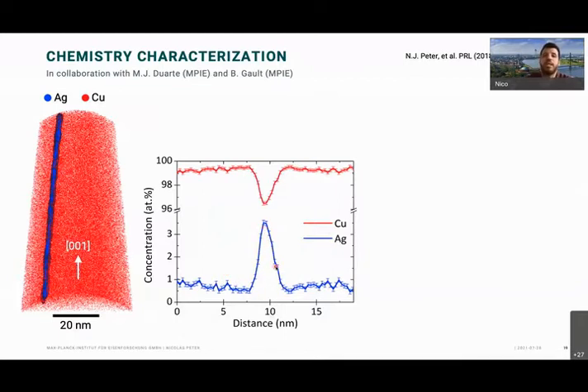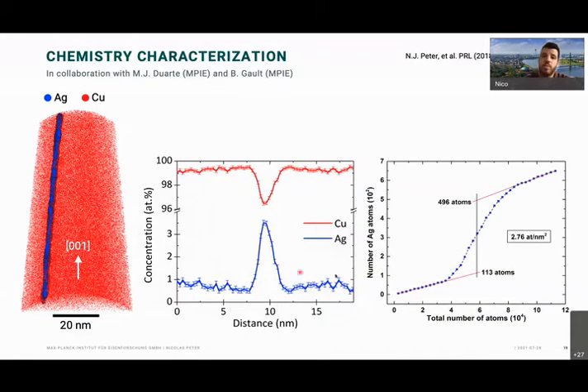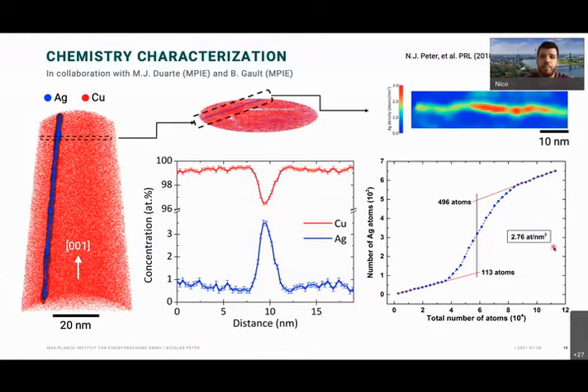of silver accumulated. And then from atom probe, we can also say the number of silver atoms is actually 2.76 atoms per square nanometer, which is the silver solute excess that we could determine here. And this fits very well to half a monolayer. So if a monolayer of silver would be decorating the 210 boundary, we would have a doubled concentration. So since we have a preferential segregation, as I explained before, this fits fairly well. What we also see, if we take a cross section through there, we do see that we do have this faceted behavior of the boundary as well as we saw it in STEM.